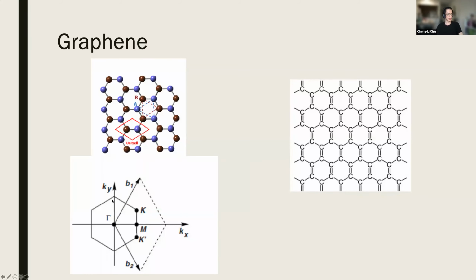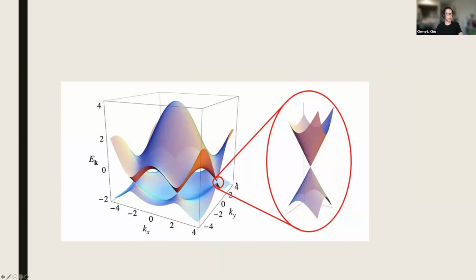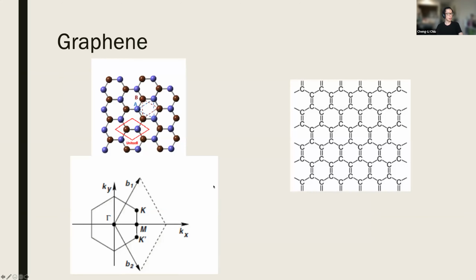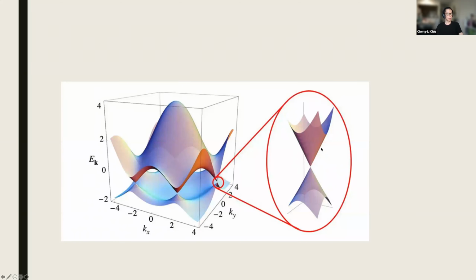And the Brillouin zone will become like a hexagonal lattice. This material is pretty interesting because if you calculate the band structure using a tight-binding model, you will get a Dirac cone at the K boundary. You can think of it like this: for the free electron, when we calculate the band structure, it has a parabolic dispersion. But in graphene, when you calculate it, the dispersion becomes linear. This kind of linear behavior is more like a photon. So sometimes we call this a massless fermion in graphene.